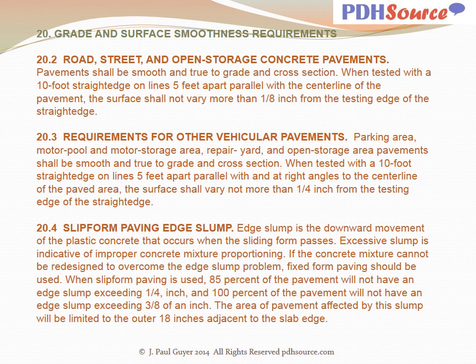With regard to slip form paving, edge slump is the downward movement of the plastic concrete that occurs when the sliding form passes. Excessive slump is indicative of improper concrete mixture proportioning. If the concrete mixture cannot be redesigned to overcome the edge slump problem, fixed form paving shall be used. When slip form paving is used, 85% of the pavement will not have an edge slump exceeding 1/4 inch, and 100% of the pavement will not have an edge slump exceeding 3/8 of an inch. The area of pavement affected by this slump will be limited to the outer 18 inches adjacent to the slab edge.